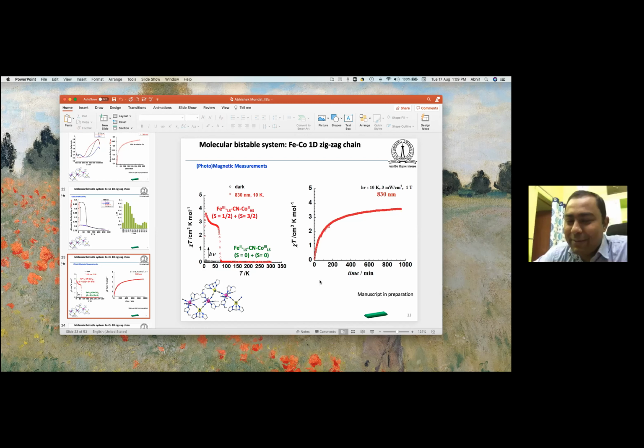Yeah, the main problem for this type of system is centering the sample. If you use a low field, you cannot center the sample very precisely, because they are all diamagnetic samples, and you are using tape of almost 10 milligram with a sample of 2 to 4 milligram. I also try to use low field, because if you use high field, at low temperature you cannot get the interaction properly and you miss some information. We usually use this 1 Tesla field because we figured out that it gives good data sets.